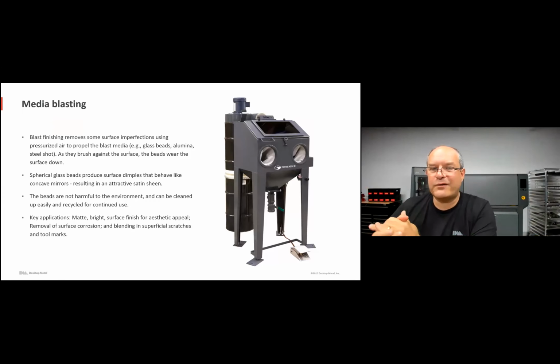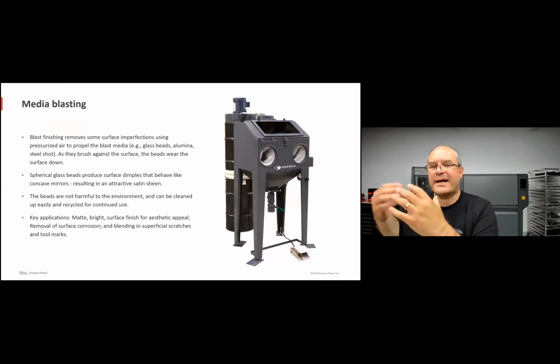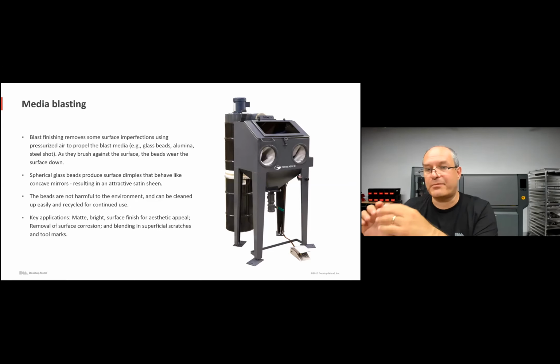Okay. Next is media blasting. So media blasting is a great way to remove surface imperfections. Your part is inside a cabinet, or you can put a bunch of parts inside the cabinet. And then under pressure, you propel the blast media, which could be glass beads, it could be a loose ceramic alumina, it could be steel shot. They all have different results. For example, the spherical glass beads impinge on the surface and produce a very small dimple, and this dimple behaves like a concave mirror, and so now you have a much more uniform satin sheen to the parts.